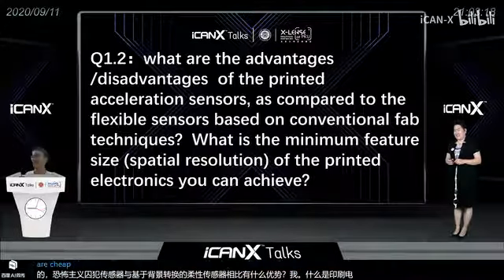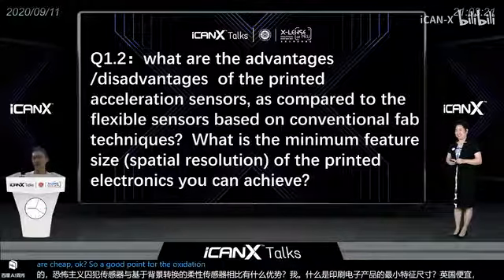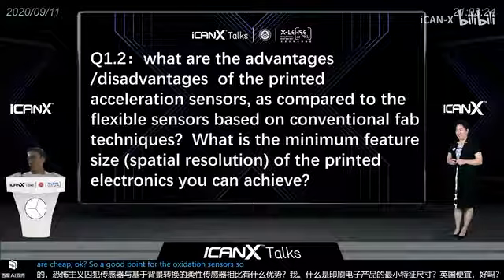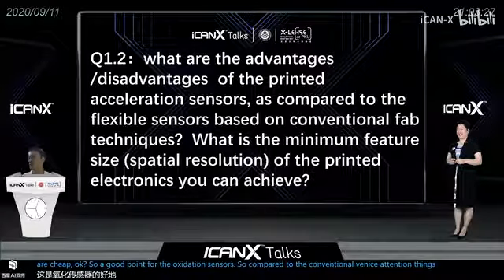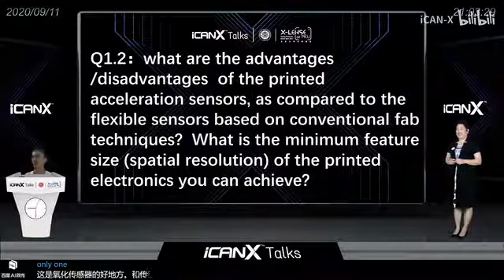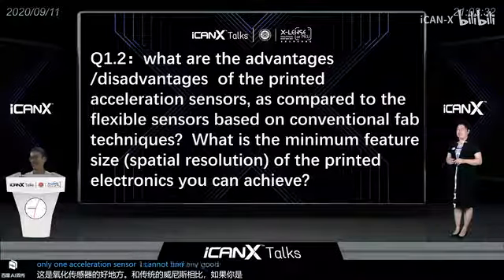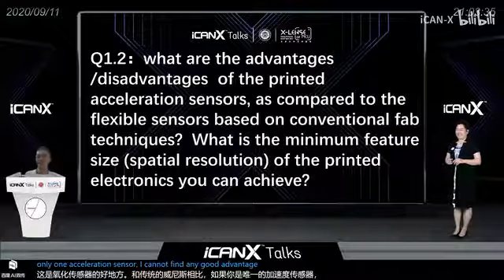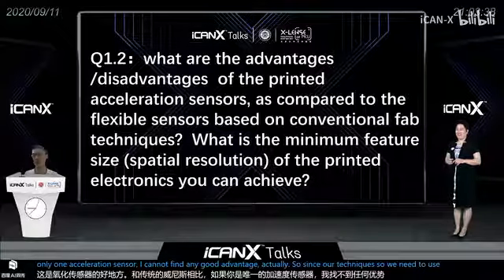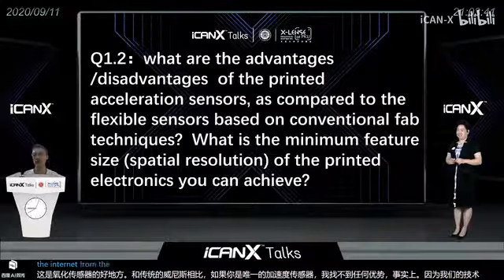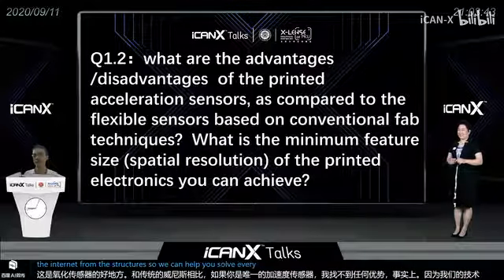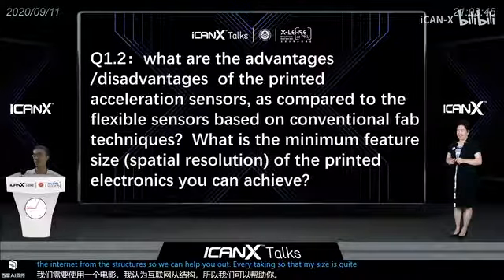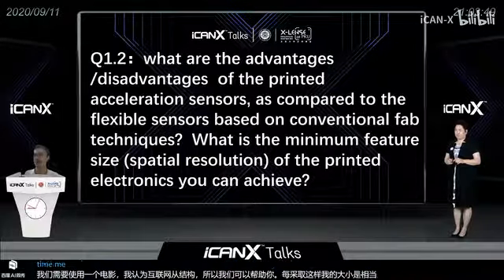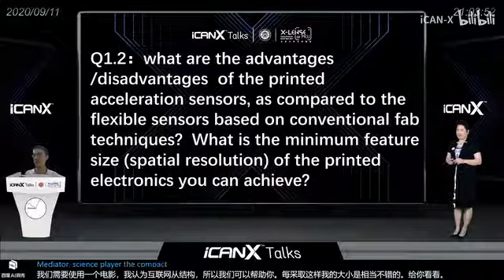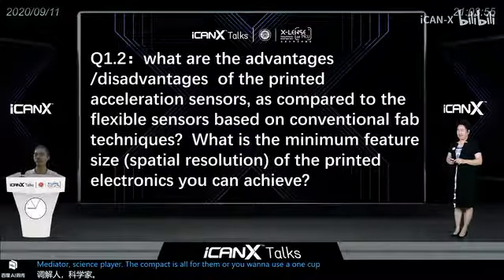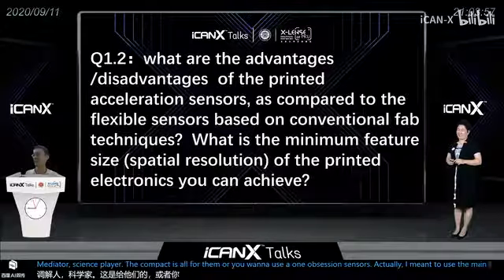Okay, good point. Actually, for the acceleration sensors, compared to conventional MEMS acceleration sensors, if you use only one acceleration sensor, I cannot find any good advantage, to be honest. With our technique, we need to use a film and also make some structures. We cannot use the lithography technique, so the device size is quite large. The minimum size is roughly 5 millimeter squared. So if you want to use one acceleration sensor, I recommend using a MEMS-based acceleration sensor.